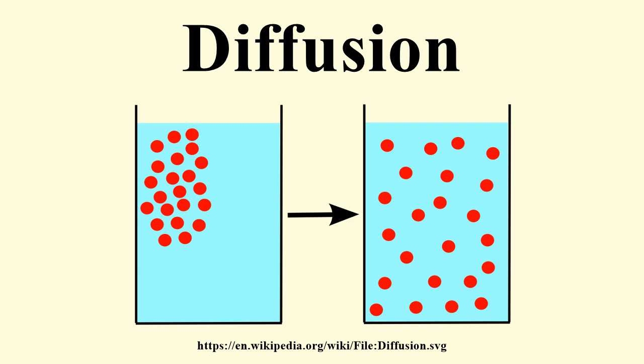Jumps on the surface and in solids. Diffusion of reagents on the surface of a catalyst may play an important role in heterogeneous catalysis. The model of diffusion in the ideal monolayer is based on the jumps of the reagents to the nearest free places. This model was used for CO oxidation on Pt under low gas pressure. The system includes several reagents on the surface. Their surface concentrations are given. The surface is a lattice of adsorption places. Each reagent molecule fills a place on the surface. Some of the places are free. The concentration of the free places is defined so that the sum of all concentrations is constant.